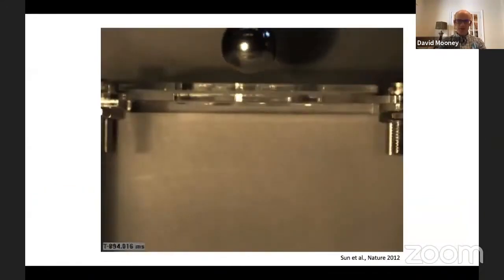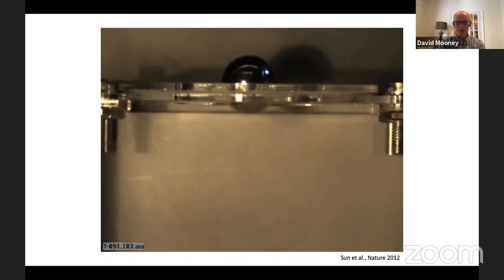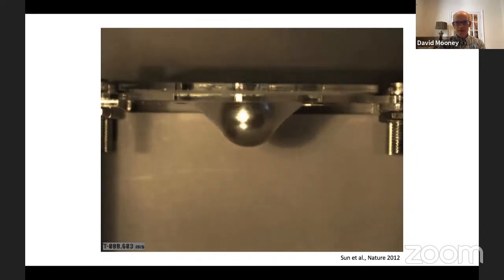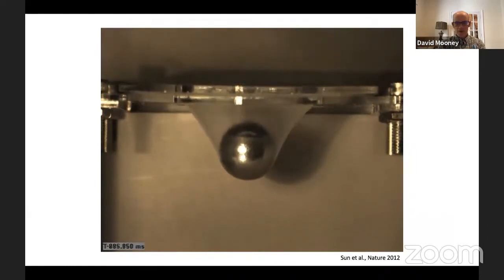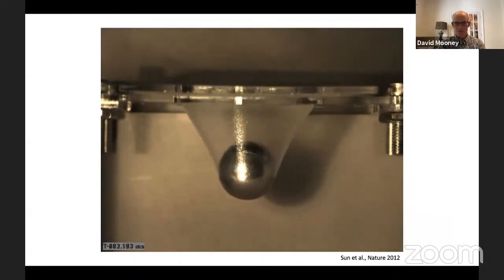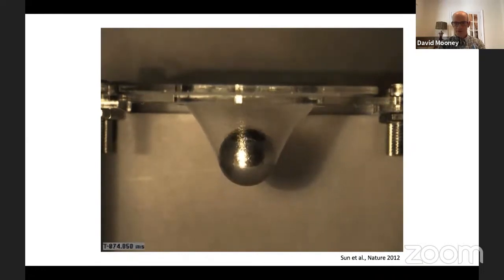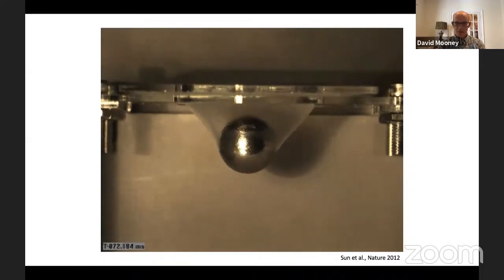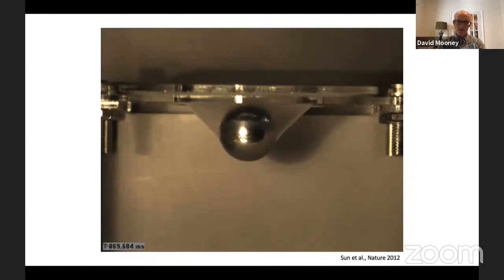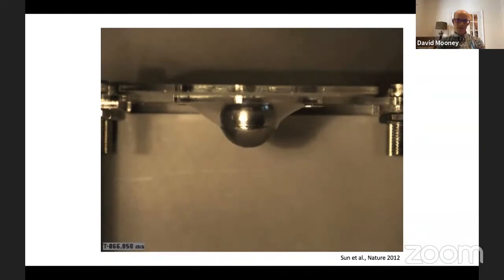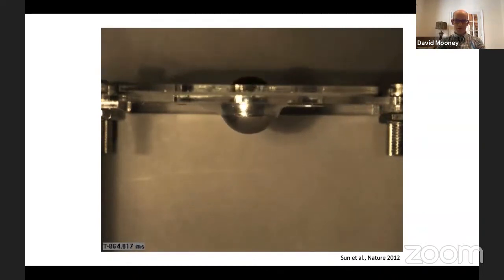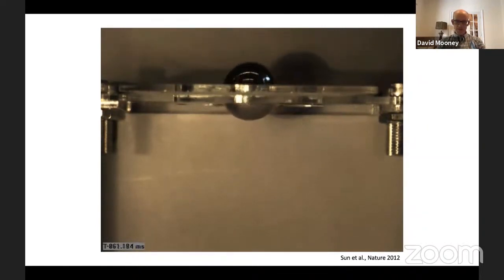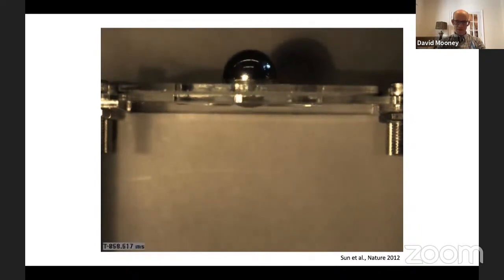They were able to demonstrate this idea pretty spectacularly. And here's a nice video demonstrating the idea, where a 1-inch steel ball was dropped from 6 feet onto a 1 millimeter thick layer of hydrogel. You can appreciate that the gel not only doesn't break, but it is actually able to return a lot of the energy back to that ball and will send it flying back up again, although it will have dissipated quite a bit of the stress. So this was a nice demonstration of some fundamental material properties, but we didn't really know what to do with this.